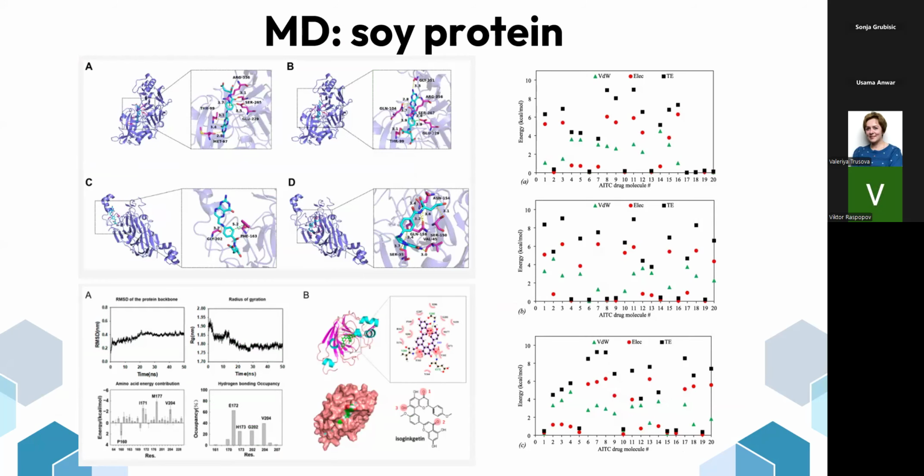Different laboratories and a lot of researchers have extensively employed molecular dynamics simulation to elucidate the binding mechanisms between different therapeutic agents, different drug molecules, and protein carriers. And these results revealed critical insight into the intermolecular forces that drive drug encapsulation and release. For example, computational studies of soy protein as a drug delivery system demonstrated that electrostatic interactions dominate the binding of polar drugs, while pi-pi stacking interactions are crucial for aromatic drug molecules.